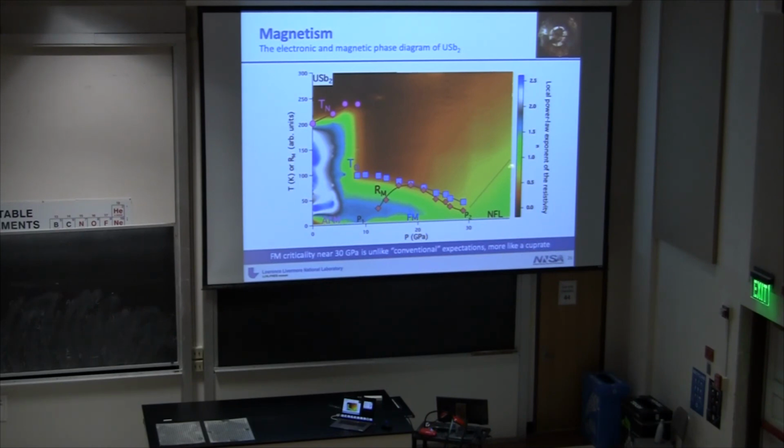And so there is data up here. This green stuff is real data. That's the local slope of the resistance, otherwise known as the derivative, and it's a power law derivative. But we have data here, we just have no transition. There's no anomalous Hall component up there, so all the Hall signal is flat. And we don't see anything in the resistance like a change in slope, or a kink or a knee or anything like that. So it really does just abruptly die somewhere between here and here. It just goes away.